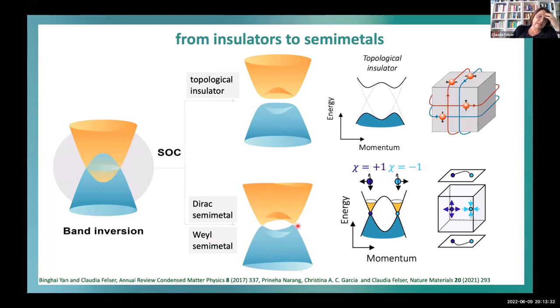And this is the case if we have crystals which have lower symmetry. And these points are also not in the electronic structure at high symmetry points. And this is, again, very interesting, because now we have even chiral electrons in the bulk. So in a Weyl semimetal, this is twofold degenerate. So we have these two points which are really distinguished. They are distinguished, for the expert, by their Berry curvature and by their different chirality. So basically, like what we know from molecules or our hands, we have the right hand and the left hand, and we cannot bring them to coincidence because they are chiral.